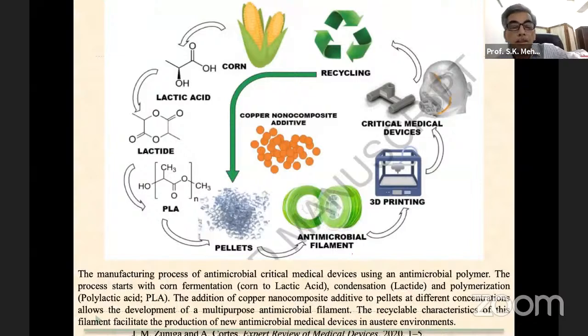Another interesting one was the manufacturing process of antimicrobial critical medical devices, and they have used antimicrobial polymer. This is because now we require so many medical devices which should be antimicrobial, and where we can use antimicrobial polymer. And the process starts with corn, which they have taken, and from this corn they created lactic acid, lactide, then through polymerization, polylactic acid, PLA, and then you can convert this into pellets.